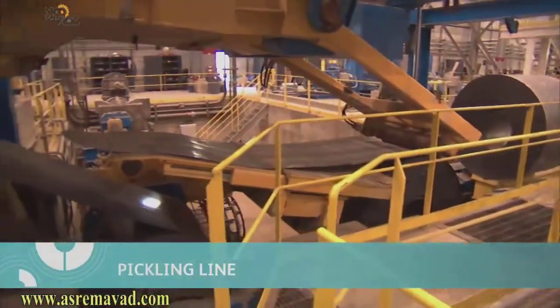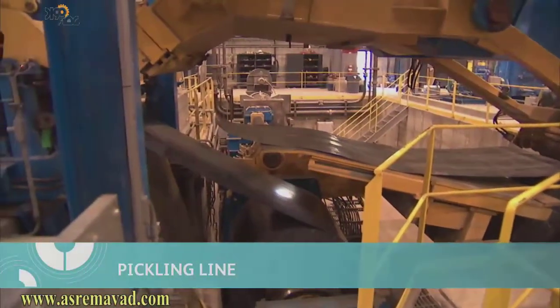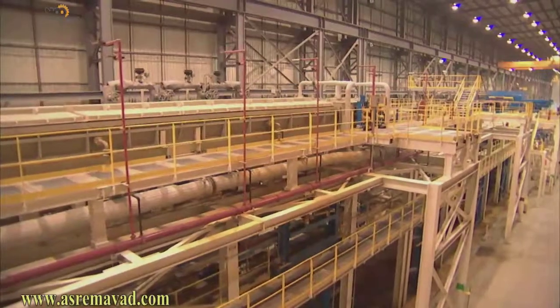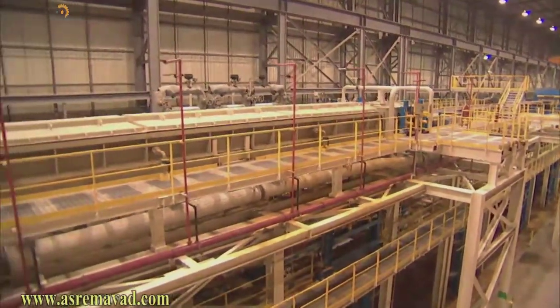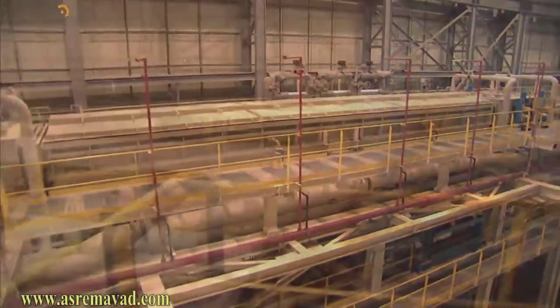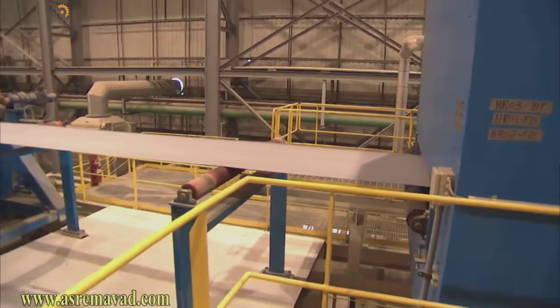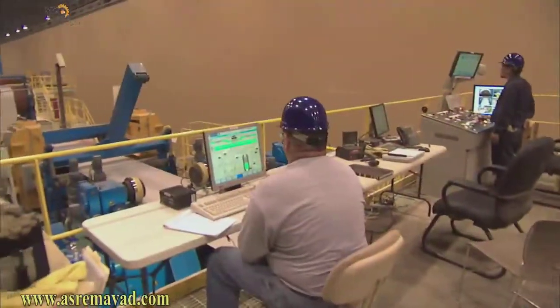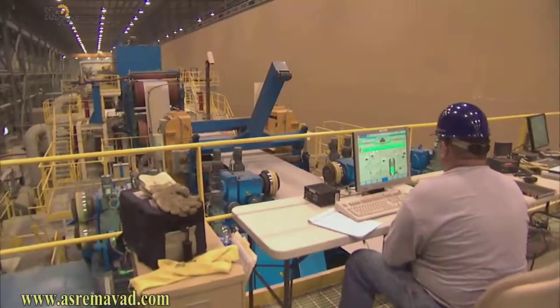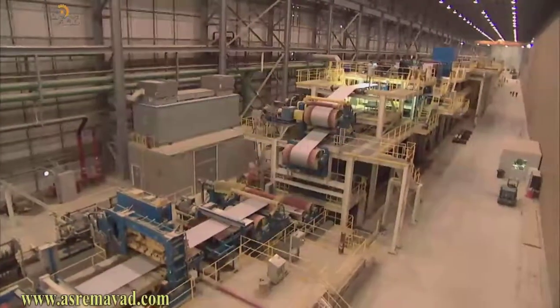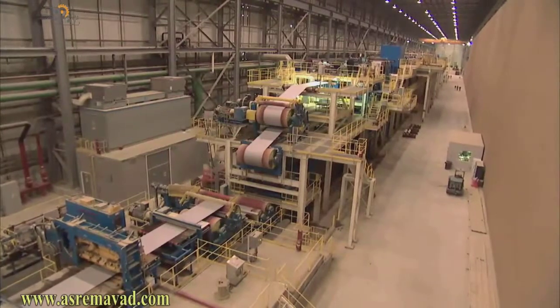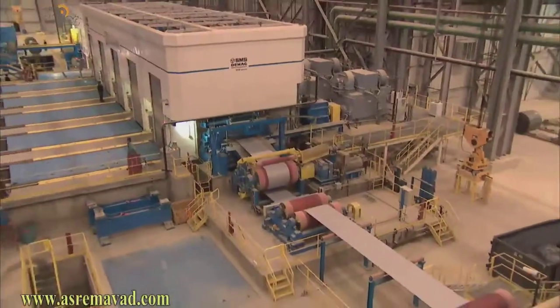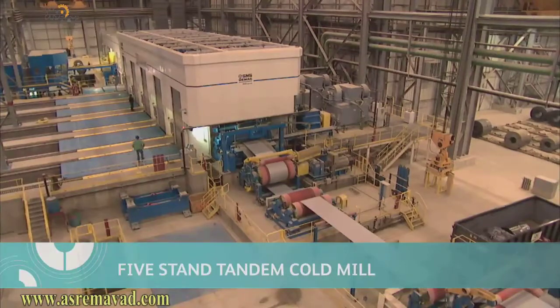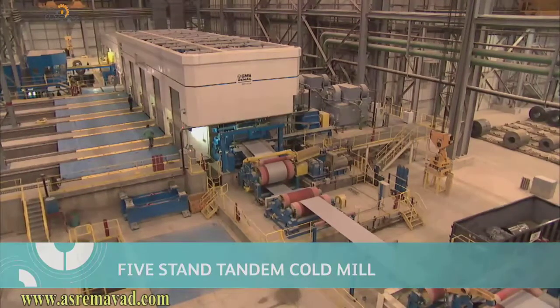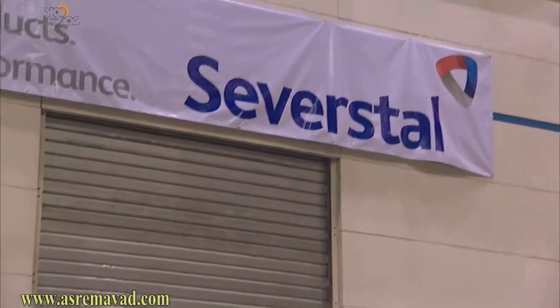The first downstream finishing process is pickling. The hot band is uncoiled and passed through a series of hydrochloric acid and water rinse tanks to remove iron oxide from the surface. Upon request, oil can be applied to the surface to help inhibit rust formation. Pickled and oiled products are typically used in heavy stampings. Severstal's continuous pickle line is unique among low-cost steel producers. The plant's pickle line is directly coupled to a 5-stand tandem cold reduction mill. This remarkable configuration is one of only 4 cold mills coupled to a pickle line in North America.